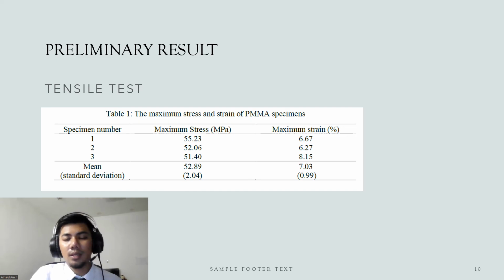3 PMMA specimen will be produced and undergo the tensile test. Firstly, the specimen will be measured using vernier caliper to see the dimension of the specimen. Next, using the tensile universal testing machine, the specimen will be loaded in the machine and wait until the specimen to be fractured. The 3 sample will be undergoing the test and the stress and strain of the specimen is tabulated from the data. It shown that the specimen one having the maximum stress compared to the other 2 specimens. The mean calculated from the 3 specimens show that the maximum stress calculated is 52.89 megapascal and the max strain calculated is 7.03%.